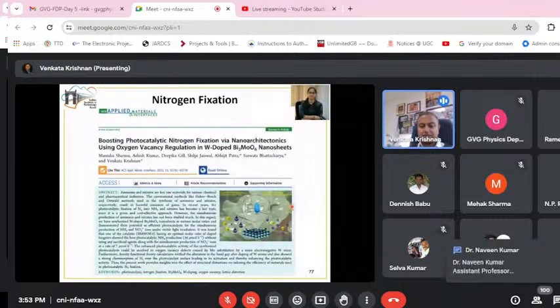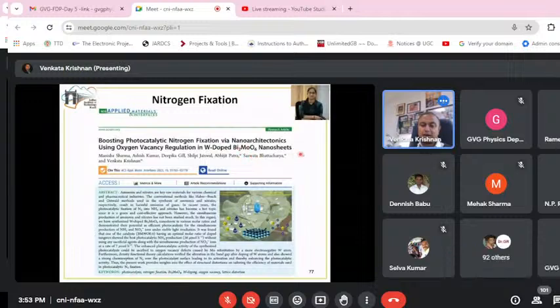Very recently, just a few weeks ago, we published another article wherein we utilized tungsten doped bismuth molybdate nanosheets, and wherein we regulated the oxygen vacancies to produce higher amounts of photocatalytic nitrogen to ammonia.